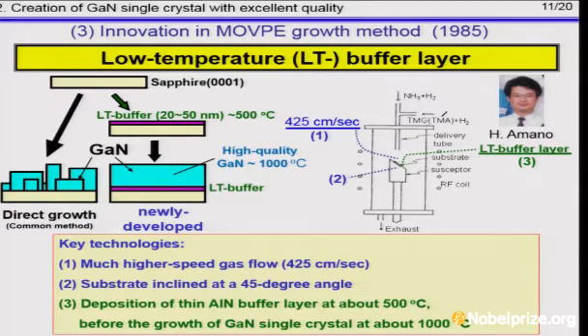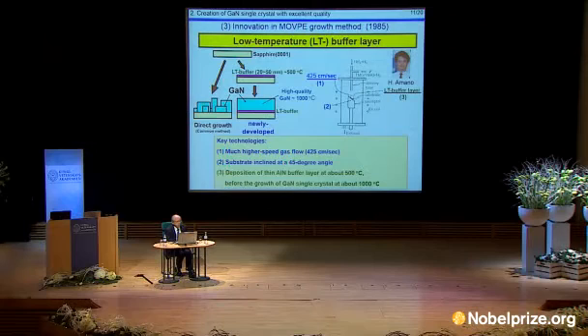In addition to the first improvement, Hiroshi Amano carried out low-temperature aluminum nitride buffer layer technology combined with a further accelerated gas flow rate of about 430 centimeters per second, and succeeded in the growth of gallium nitride single crystal with a specular surface in 1985. Details will be presented by Professor Amano.